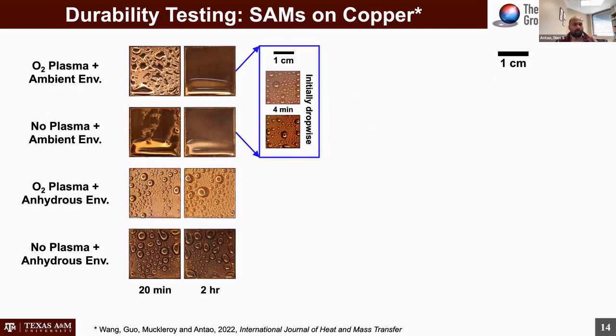Okay, so we tested 4 different types of samples. The topmost row is what typically exists in our community. So almost everyone I know oxygen plasma treats the surface and then does coating in an ambient environment. We also did no plasma treatment and coating in an ambient environment. And then we did the anhydrous environment coatings with and without oxygen plasma treatment.